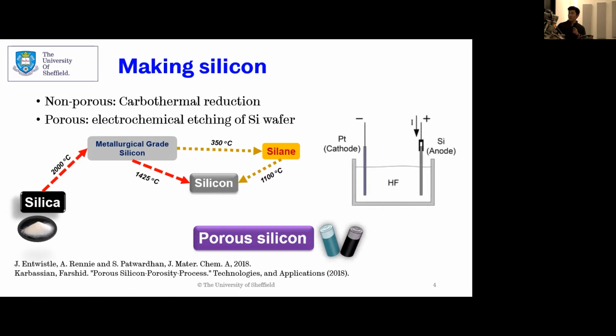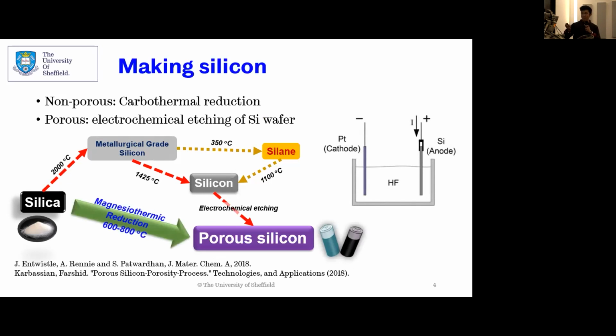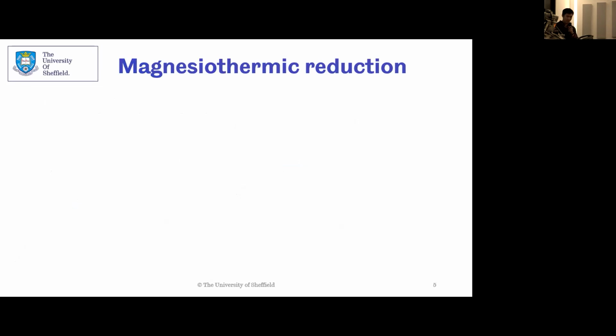To make it useful for batteries, from here to here is an electrochemical etching, which uses a corrosive media, and it's a surface method, which means you can't make it in bulk. Then you can put this into a battery. Not at the industrial scale yet is the magnesiothermic reduction, a one-step process going from silica to porous silicon, with hydrochloric acid etching, and it works at 600 to 800 degrees Celsius. So well within the limits of the melting point of silicon, and that's why this is the method I'll be studying.